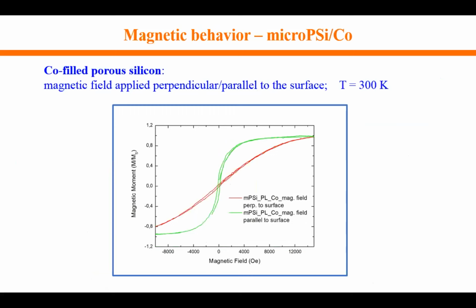So the same measurements have been done for cobalt-filled porous silicon. You also see the magnetic anisotropy between easy and hard axis magnetization. And you also see that this magnetic anisotropy is even more pronounced than for nickel samples.